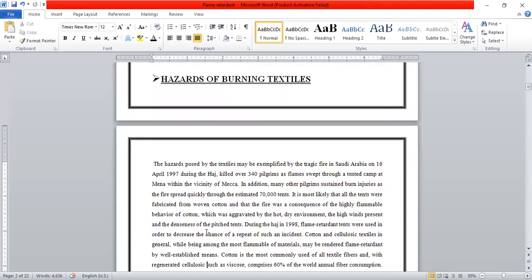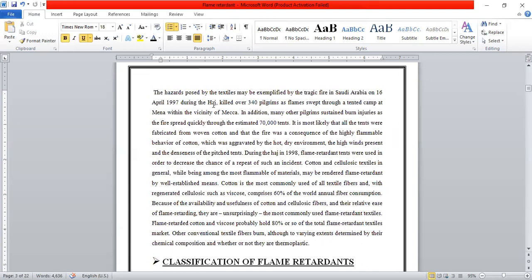Hazards of burning textiles. The hazards posed by textiles may be exemplified by the tragic fire in Saudi Arabia on 16 April 1997 during the Hajj, which killed over 340 pilgrims as flames swept through a tented camp at Mina within the vicinity of Mecca. In addition, many other pilgrims sustained burn injuries as fire spread quickly through the estimated 70,000 tents. It is most likely that all the tents were fabricated from woven cotton and that the fire was a consequence of the highly flammable behavior of cotton, which was aggravated by the hot, dry environment, the high winds present, and the denseness of pitched tents. During the Hajj in 1998, flame retardant tents were used in order to decrease the chance of a repeat of such an incident.